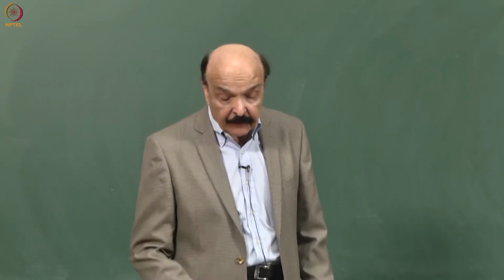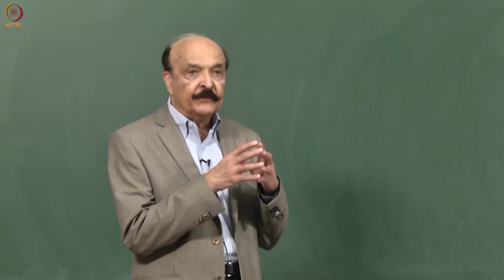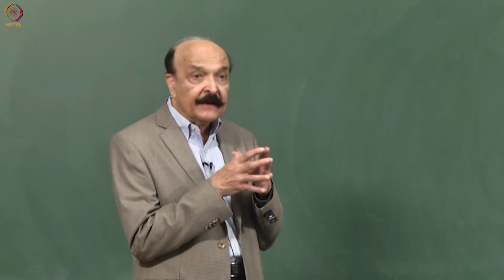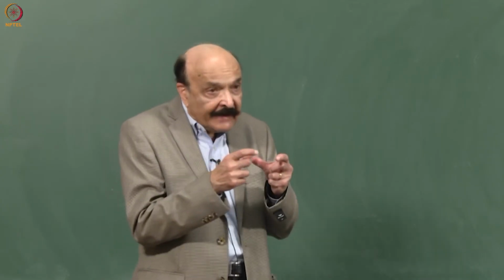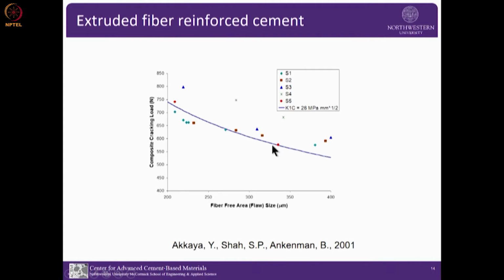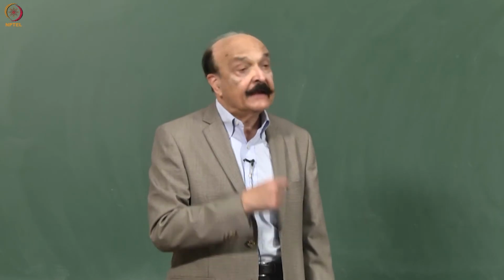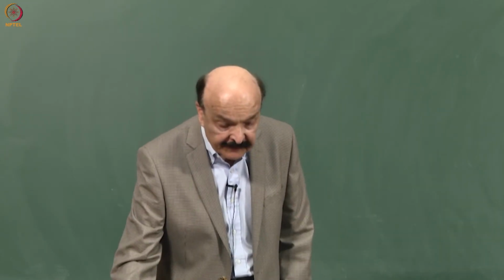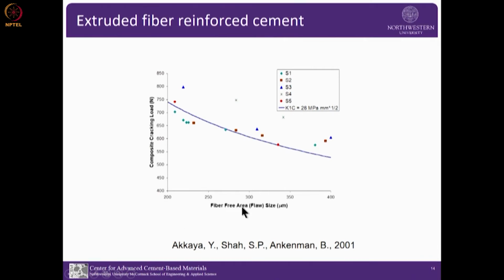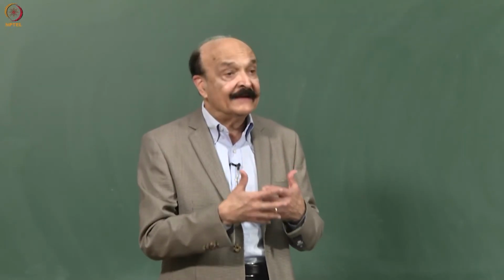Now, what we found out, if you recall, I told you that the effect of closer spacing did not work with the macro fiber, but with the small fibers we have now. So what we did, all the material had the same volume of PVA fibers, but because of dispersion or other reasons, we got different results. And so we cut the specimen and using SEM calculated the fiber free area, assuming the fiber free area is the flaw size. So here we calculated the fracture strength of the composite versus fiber flaw size, and we did get somewhat similar to Griffith fracture criteria. But the flaw size has to be in a small enough range, and the fibers have to be in the size range that they can interact with the cracks.